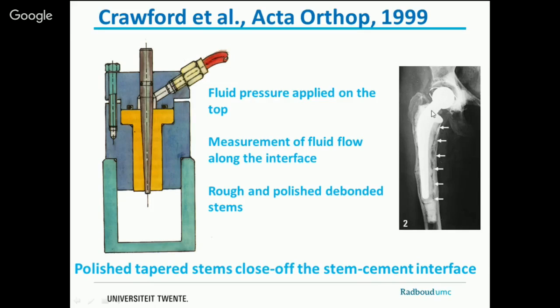And if there is space between the implant and the cement, they're going to travel around the stem, between the stem-cement interface, and they could get out, for example, here, if there is a cement fracture. Yeah, they could travel that distance, and then they can resorb bone. They can lead to osteolysis distally, at the distal site where the wear particles are formed.